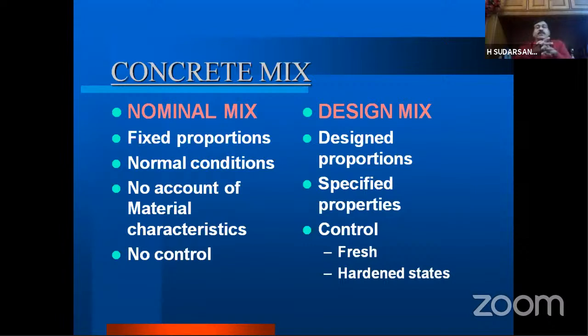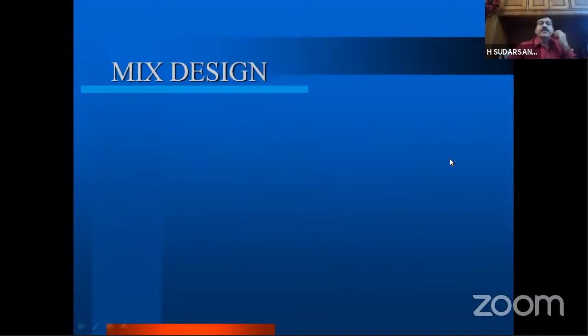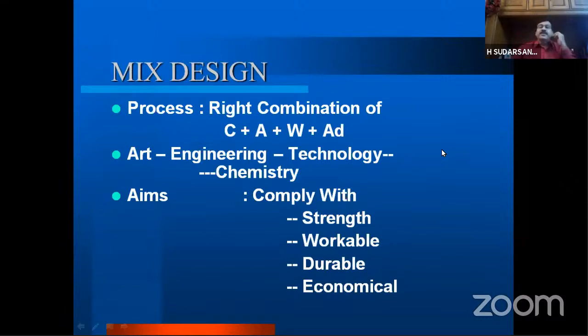So when you come to concrete mixes, we have the nominal mix and we have a design mix. In case of a normal concrete, we may go with a nominal mix, but for high performance concrete, you don't have any other method other than design mix. You have to use the design mix. So in the nominal mix, you have fixed proportions, normal conditions, no account of material characteristics and no control. Whereas in the design mix, the proportions are designed and the specified properties are satisfied. And we have a good control on fresh and hardened states. That is why in case of high performance concrete, we have to always go for a design mix.